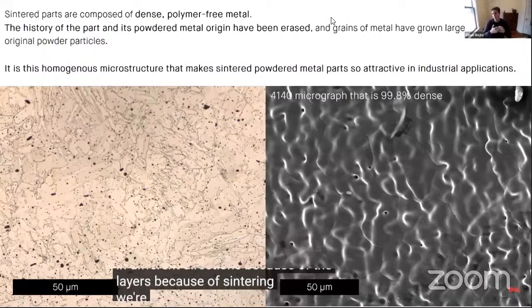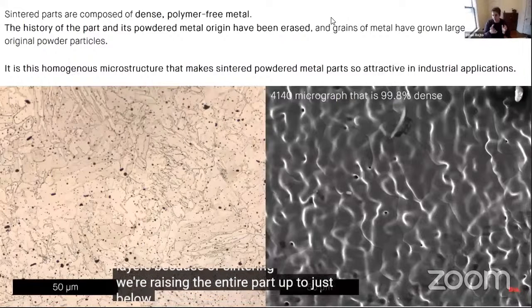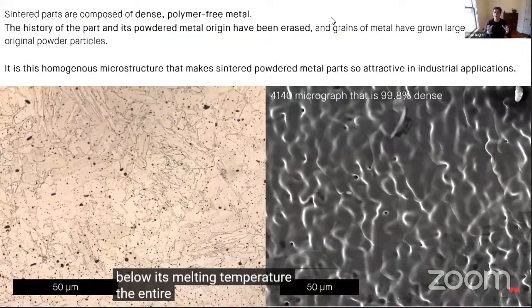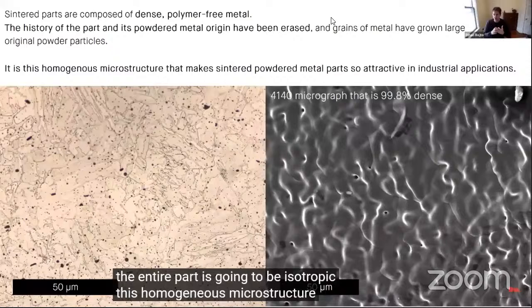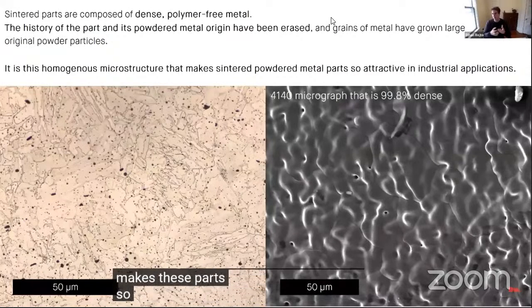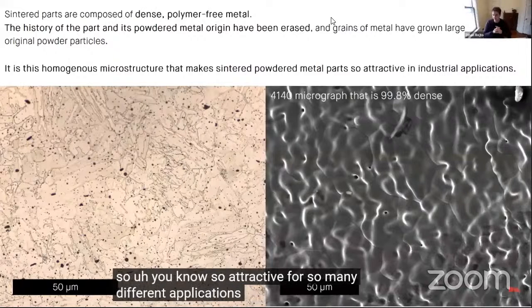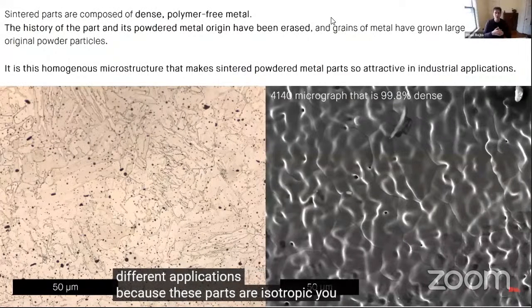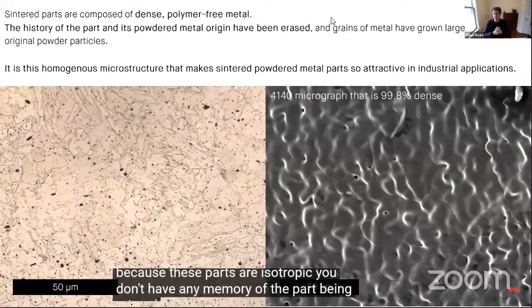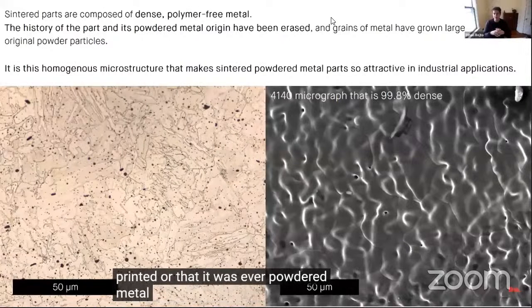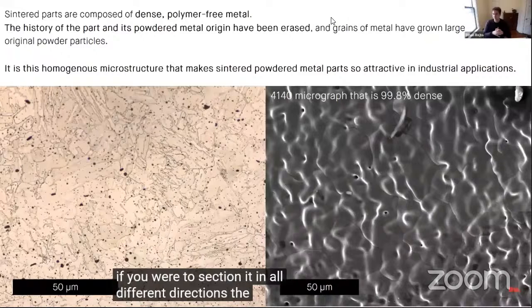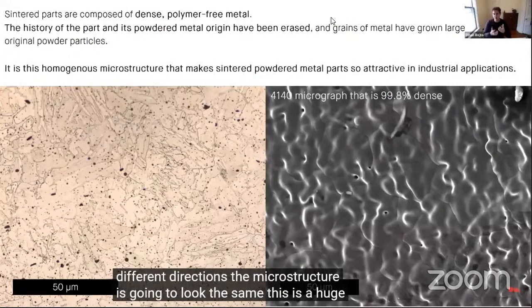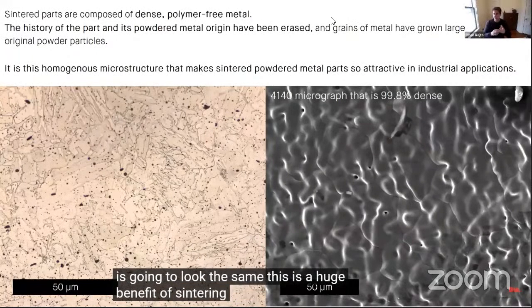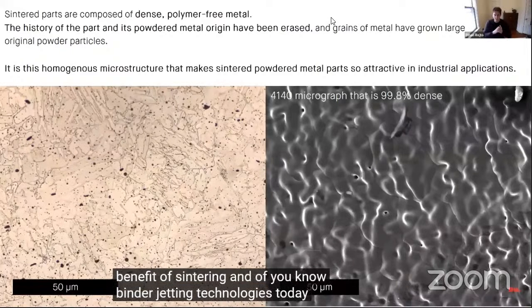Because of sintering, we're raising the entire part up to just below its melting temperature. The entire part is going to be isotropic. This homogeneous microstructure is what makes these parts so attractive for so many different applications. Because these parts are isotropic, you don't have any memory of the part being printed or that it was ever powdered metal. If you were to section it in all different directions, the microstructure is going to look the same. This is a huge benefit of sintering and of binder jetting technologies today.